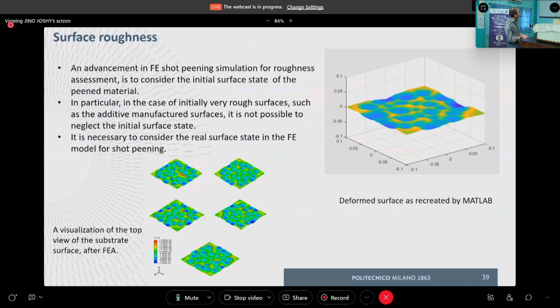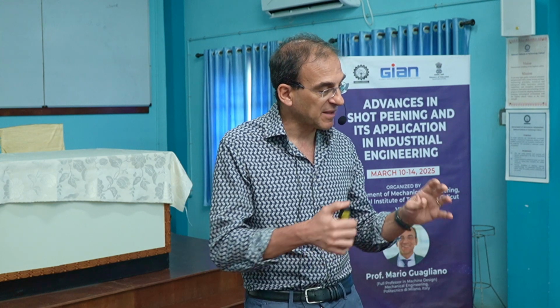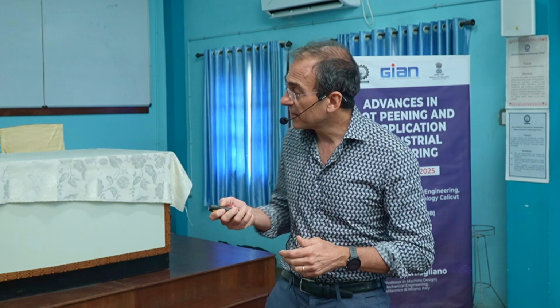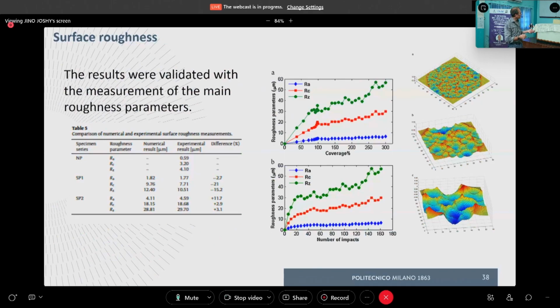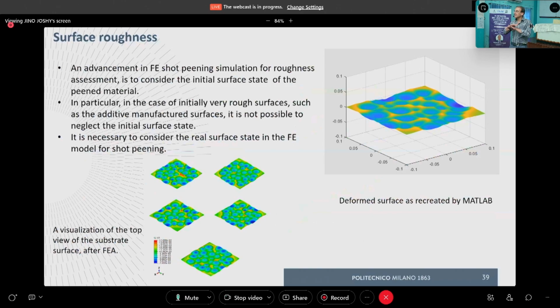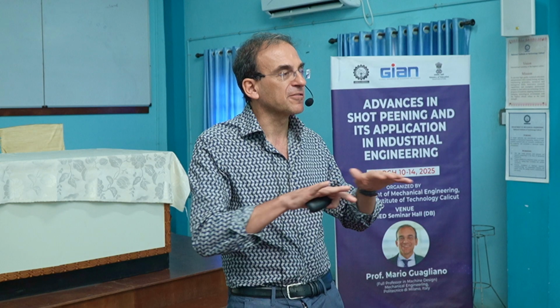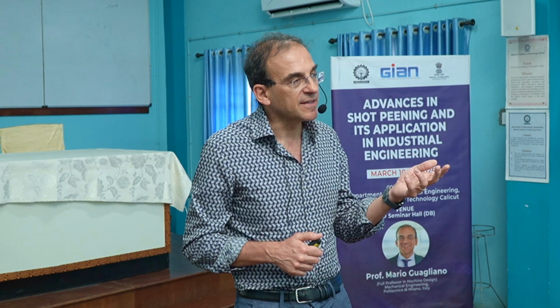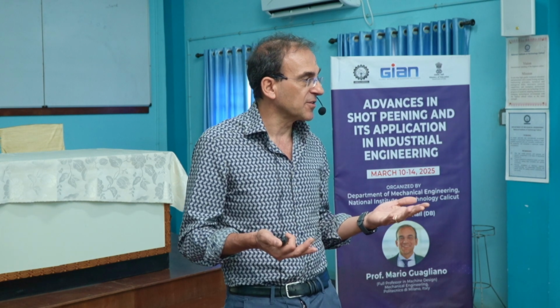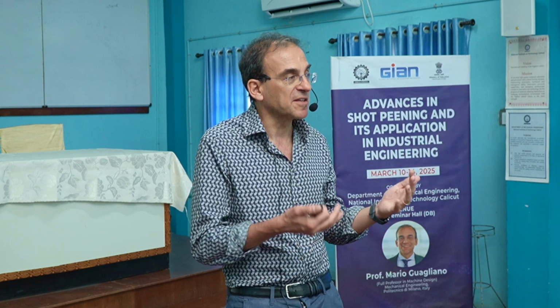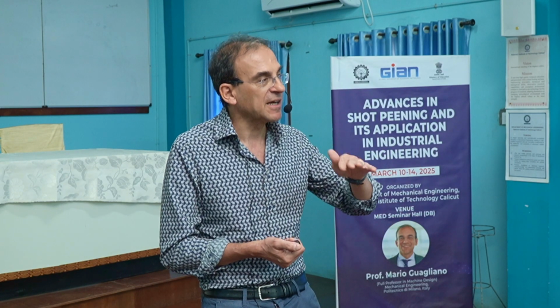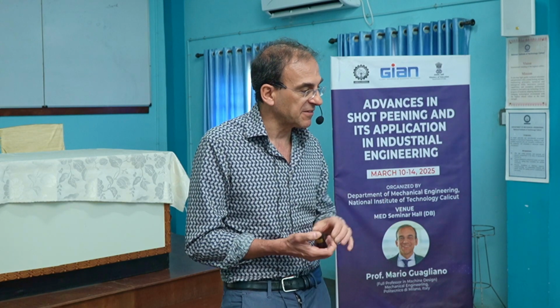An improvement of this model can be done by considering the initial starting point. About this I will discuss tomorrow, about additive manufacturing, but just to anticipate, with this model we are starting by simulating shot peening on a perfectly smooth surface, flat without any asperity. In reality, no, this is not the real condition. We can have a very good smooth surface and it can be assimilated to a perfect surface. Sometimes we have some deviation, we have a roughness that cannot be neglected, even if very good.